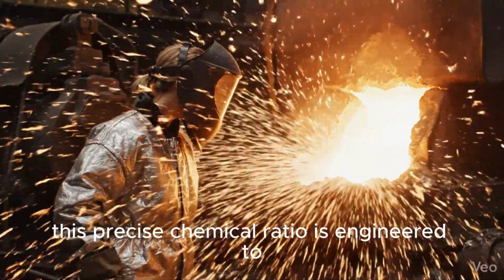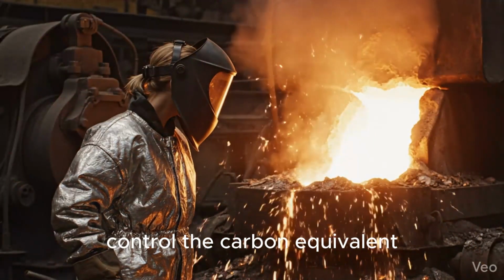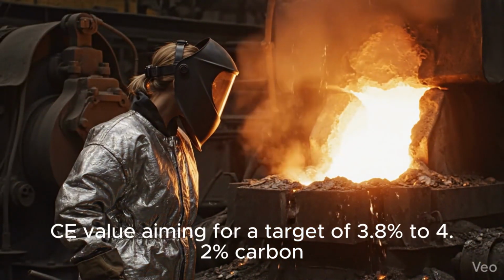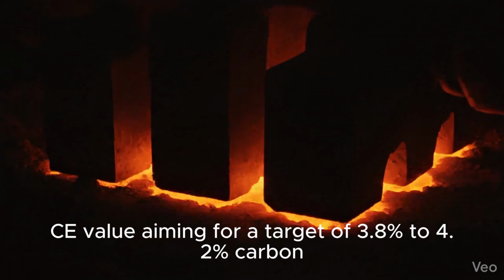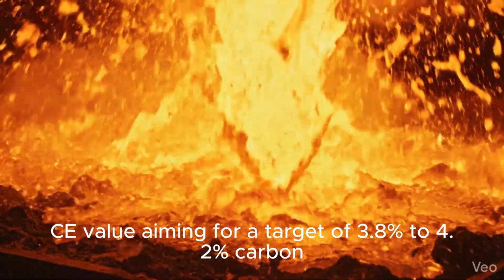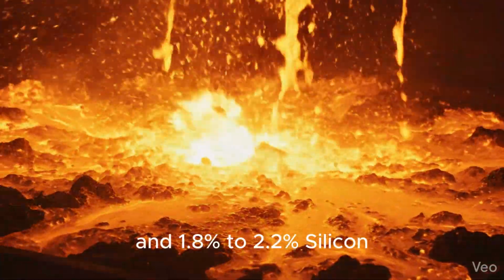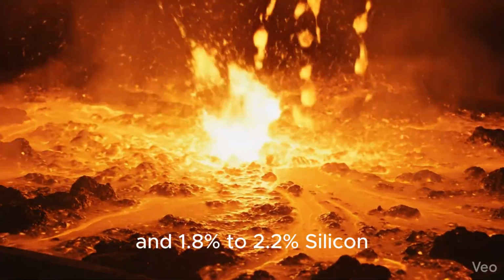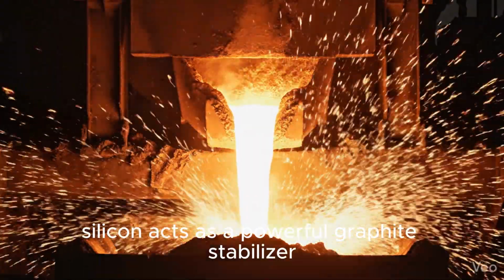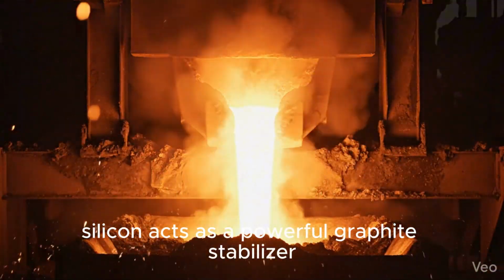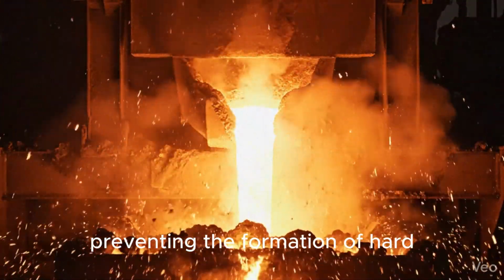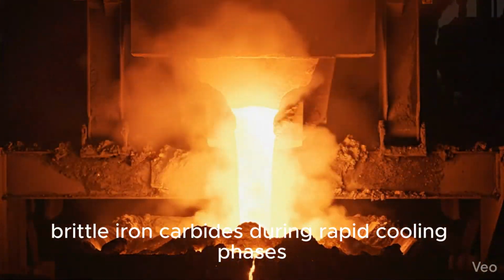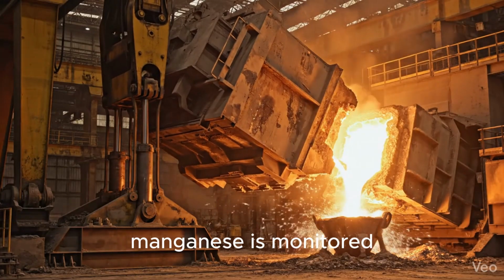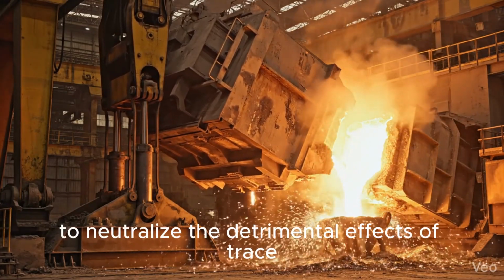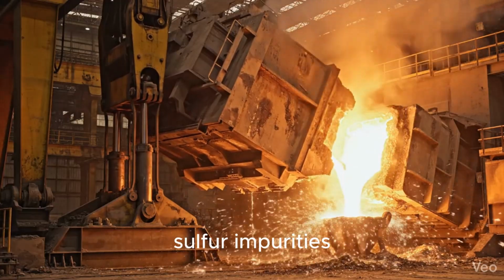This precise chemical ratio is engineered to control the carbon equivalent, CE, value. Aiming for a target of 3.8% to 4.2% carbon, and 1.8% to 2.2% silicon. Silicon acts as a powerful graphite stabilizer, preventing the formation of hard, brittle iron carbides during rapid cooling phases. Manganese is monitored to neutralize the detrimental effects of trace sulfur impurities.